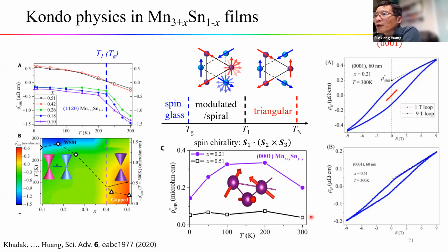With extended magnetic doping, say magnetic impurities like manganese, the spins are likely to be randomly oriented. That gives rise to some positive and some negative spin chirality and reduces the net spin chirality. So that's what we observed here.